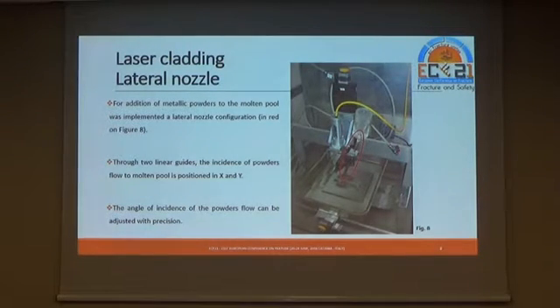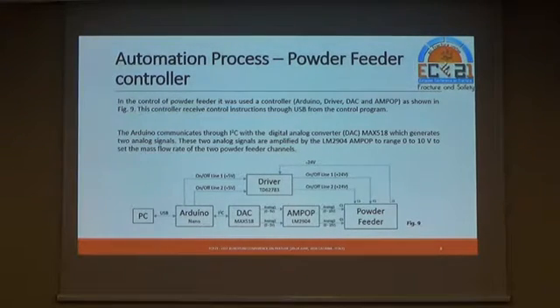For addition of metallic powders to the molten pool, a lateral nozzle configuration was implemented. Through 2 linear guides, the incidence of the powder flow on the molten pool can be positioned in X and Y. The angle of incidence of the powder flow can be adjusted with precision. For the control of the powder feeder, a controller was used, with an Arduino, a drive, a DAC, and an AMPOP, as shown in the figure. This controller received control instructions through USB from the control programs.